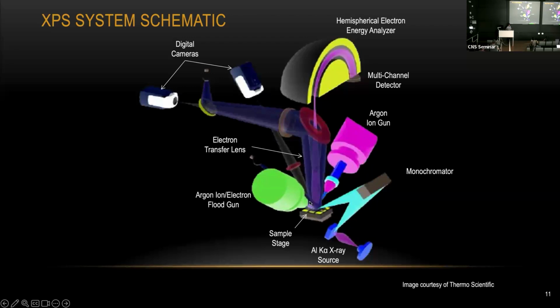And in most XPS systems, you also have an ion gun for etching and a flood gun for neutralization. The signal coming out from the sample will go through some lens and eventually go through the analyzer and detector. Everything you're seeing here is actually housed in a high vacuum chamber. For XPS measurement, we're dealing with electrons and ions, and these particles are not going to survive in air. So you need to be housed in an ultra high vacuum chamber so you can get enough signal.